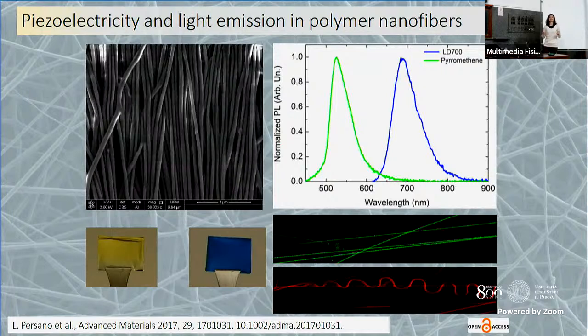Electromechanical coupling can take place at the fiber level, as we have seen so far, but also at the molecular scale. In order to exploit this coupling, we build hybrid fibers where, directly in the solution used for electrospinning, we put in contact a piezoelectric polymer and a light emitting dye. These are the fibers that we achieved. The point is that by using electrospinning, by blending different materials with different functionalities, you can get one material with both functionalities. So we have light emission from these fibers and piezoelectricity as well.